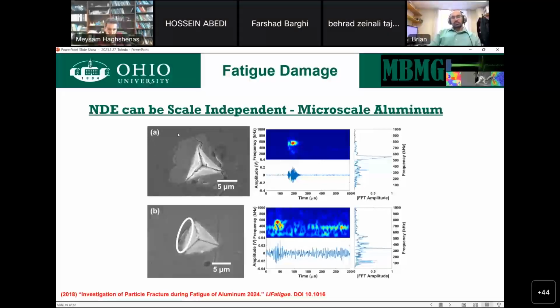This is an aluminum 2024 series alloy that we zoomed in on, and we applied a nano indentation directly on one of the precipitates. In this case, it's actually more of a particle. It's a little bit larger than a typical precipitate. And we initiated this fracture event to happen and recorded what that signal looked like. We did the same thing indenting straight on the aluminum matrix itself, and we observed a much different response, an order of magnitude weaker in the burst characteristics and the frequency content. So very different signals indenting the same material in just two different locations.